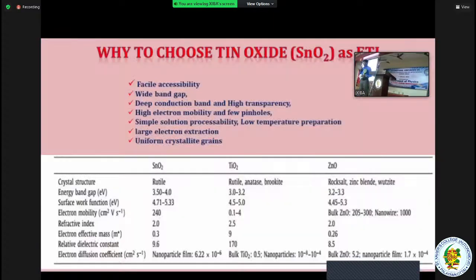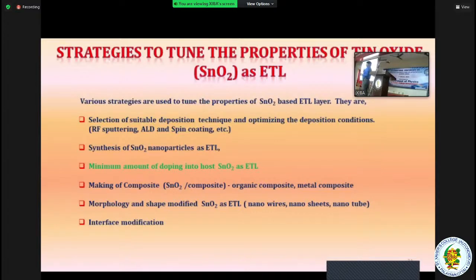So that's why we preferred using tin oxide, not titanium oxide. When we use tin oxide instead of titanium oxide, these are some advantageous properties: wide band gap, deep conduction band, high transparency, high electron mobility, large electron extraction, and uniform crystalline grain. These are some of the advantageous properties compared to titanium oxide.